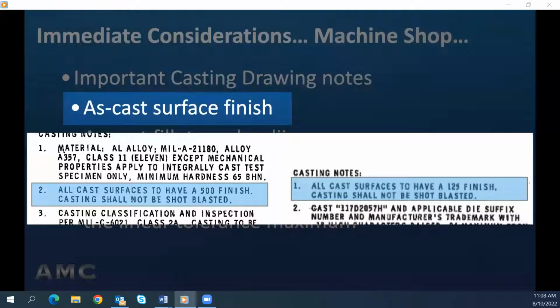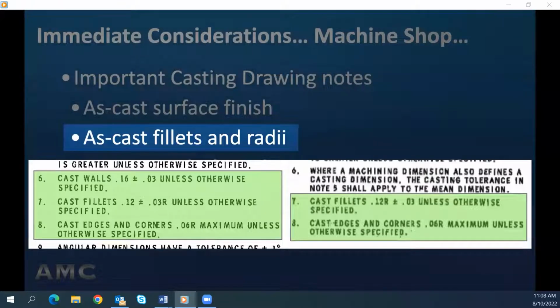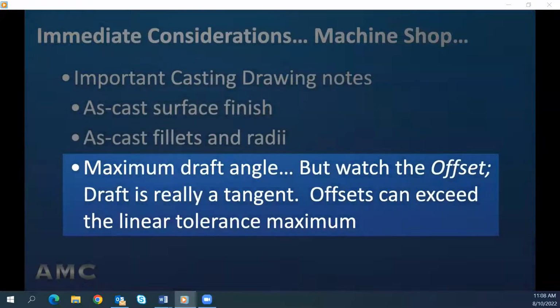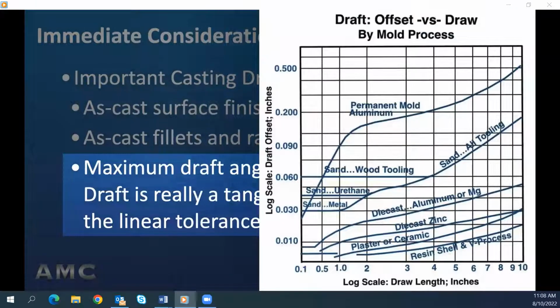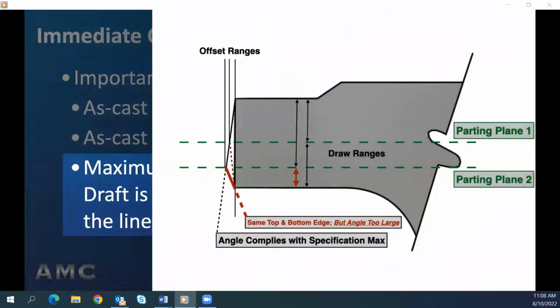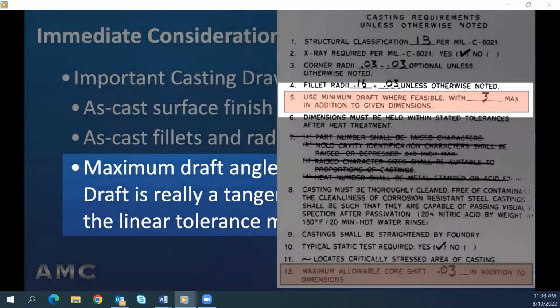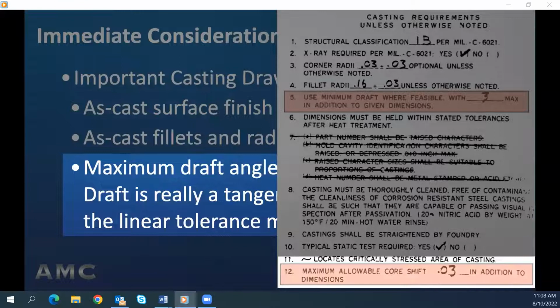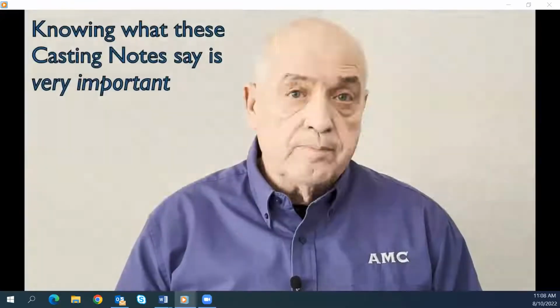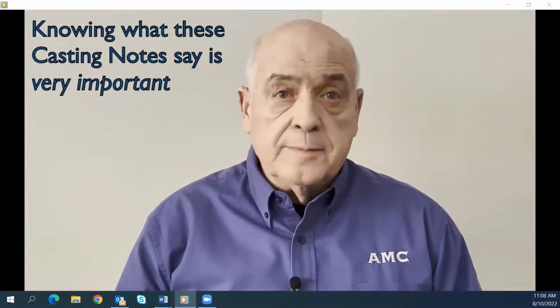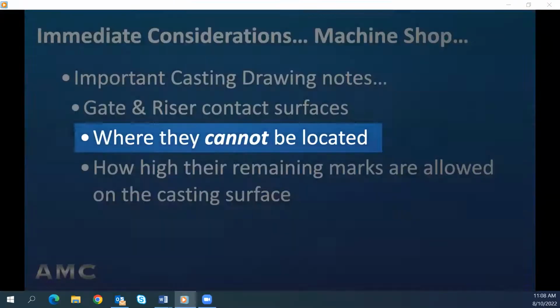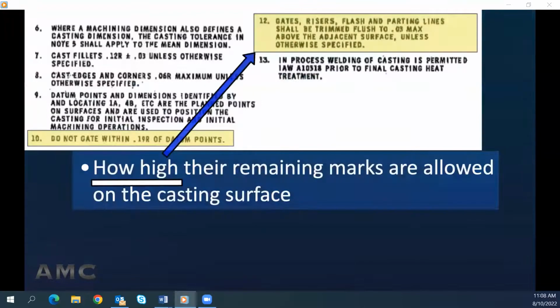Drawing notes regarding as-cast surface finish. Drawing notes regarding as-cast fillets and radii. Drawing notes regarding maximum draft angle, but watch the offset. Draft is really a tangent. Offsets can easily exceed the linear tolerance maximum. Here, however, the drawing note allows 3-degree maximum draft, and the draft offset can be added to a feature dimension plus tolerance. Notice also that core shift is allowed up to 0.03 inch as additive to the feature dimension plus tolerance. Knowing what these notes say is really important. Drawing notes regarding gate and riser contacts, where they cannot be located and how high their remaining marks are allowable